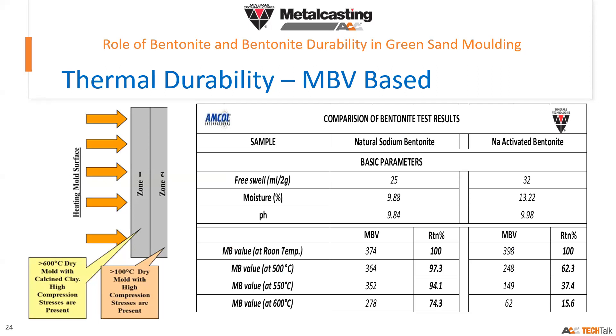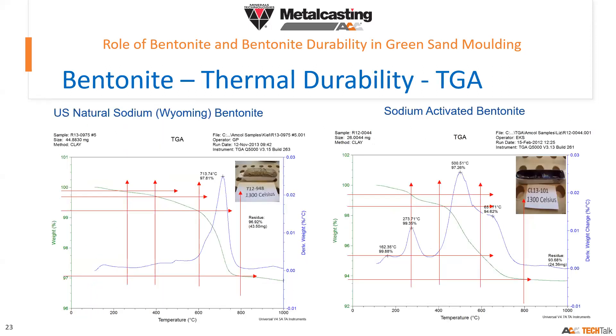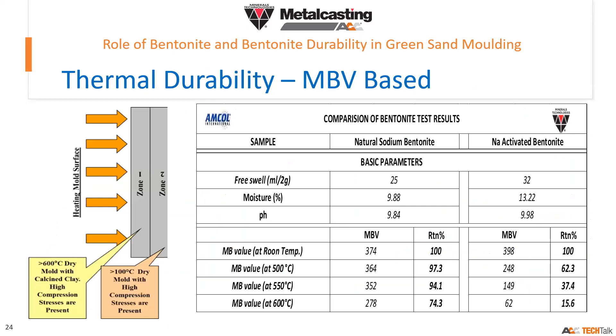The temperatures of 500°C, 550°C, and 600°C were chosen based on TGA analysis — observing at what temperature range the drop is happening. To quantify it further, we qualify based on the MBV method. From the table, you can see that natural sodium bentonite tested at room temperature without calcination showed 374 MBV, whereas activated bentonite showed a higher MBV of 398.